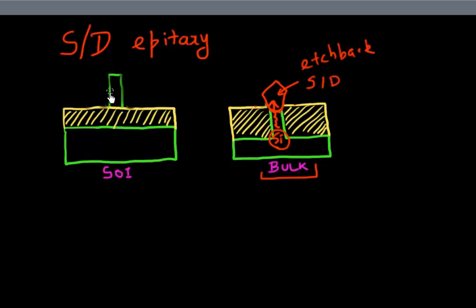On the other hand, if I come to this SOI substrate and I etch off this fin in the source drain region, there's nothing left below from which I can grow. So I can't grow my source drain region over here because there's no template available for growing this crystalline region back. So that's another limitation of SOI flow.